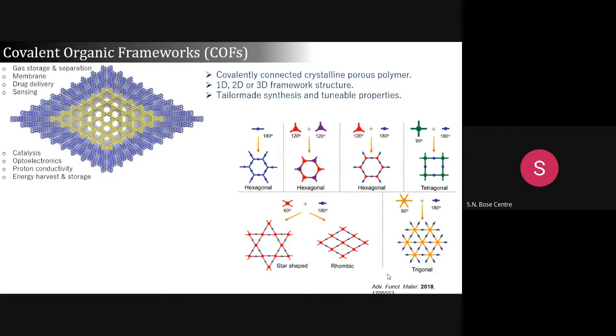And this material can be synthesized very easily by just taking the ligand with a particular geometry. Suppose you take a linear one, you can condense this one in a hexagonal fashion. If you take a trigonal one with a particular angle, you can also get a hexagonal one. Similarly, trigonal with a ditopic ligand, you can get hexagonal. Tetragonal with a ditopic linker, again you can get a tetragonal one. Kagome lattice, and whatnot, different kinds of arrangement you can do. By arranging the chromophore in different fashion, you can really tune their property, band gap, and efficiency for photocatalysis and other applications, which I will be explaining in the next slide.